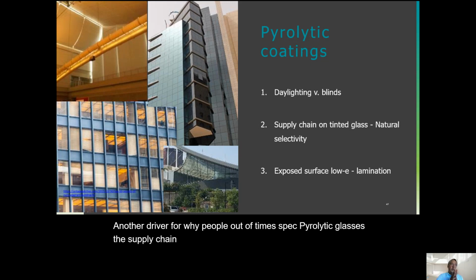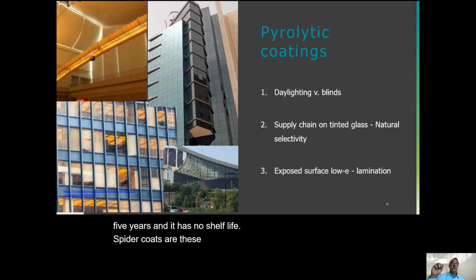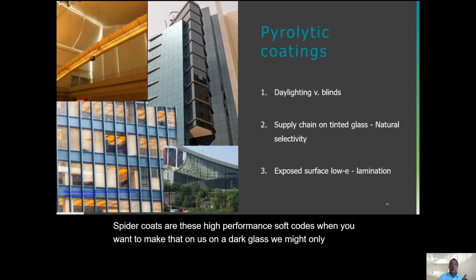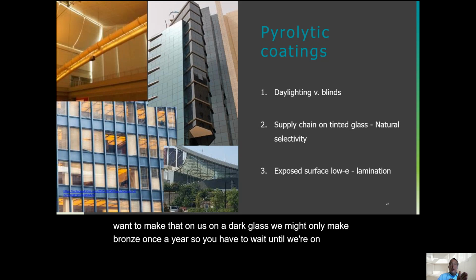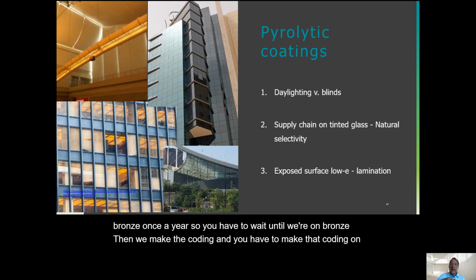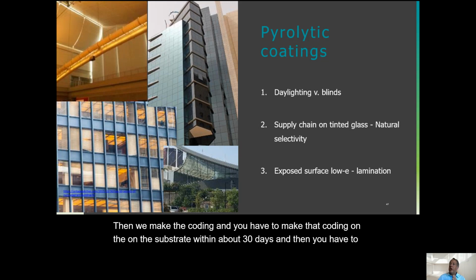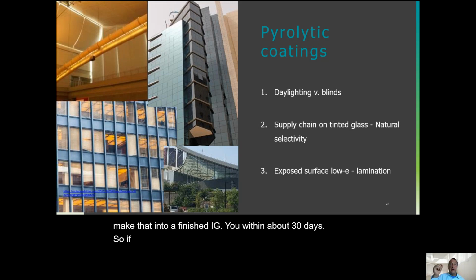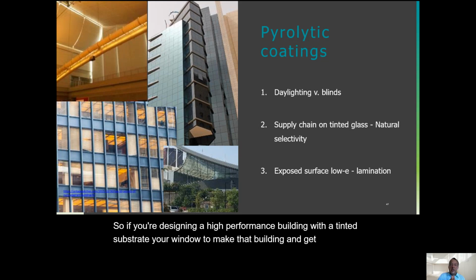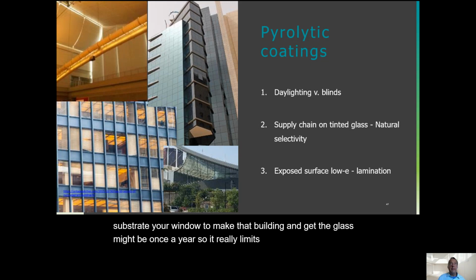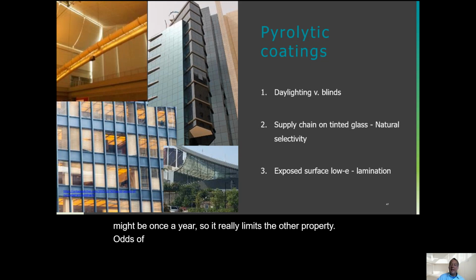So when we make hard coats or pyrolytic coatings, you can make a bronze glass or a green glass, and you put this coating on, you could put it in the warehouse for 5 years and it has no shelf life. Sputter coats are these high performance soft coats. When you want to make that on a dark glass, we might only make bronze once a year. So you have to wait until we're on bronze, then we make the coating, and you have to make that coating on the substrate within about 30 days. And then you have to make that into a finished IGU within about 30 days. So if you're designing a high performance building with a tinted substrate, your window to make that building and get the glass might be once a year. So it really limits the other parts of the project that you maybe didn't consider.